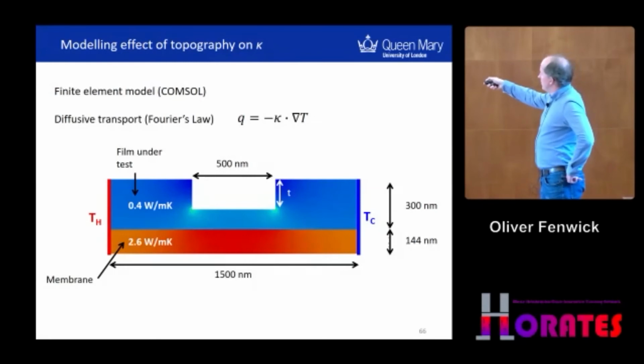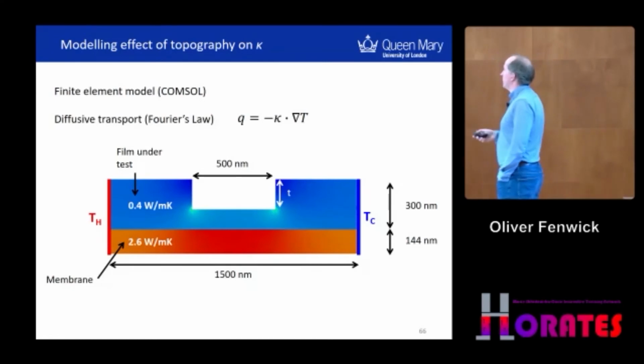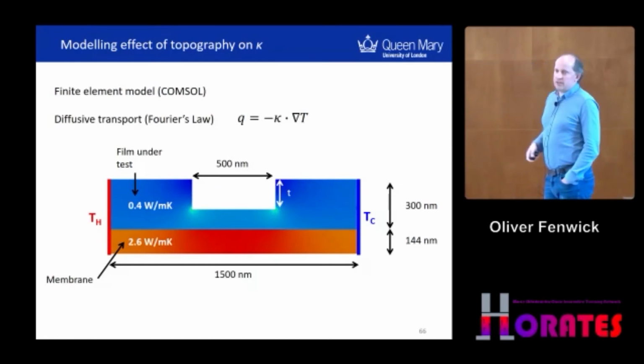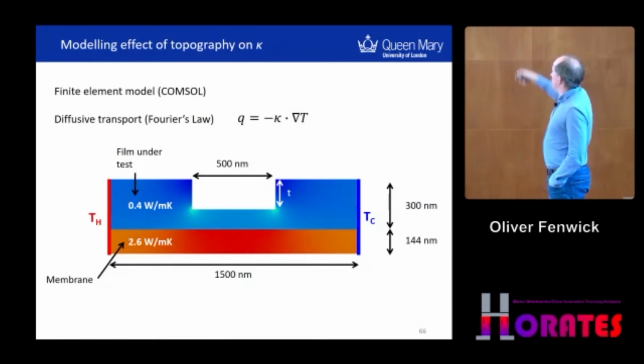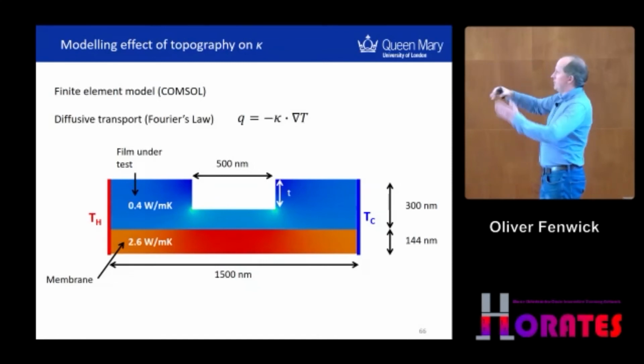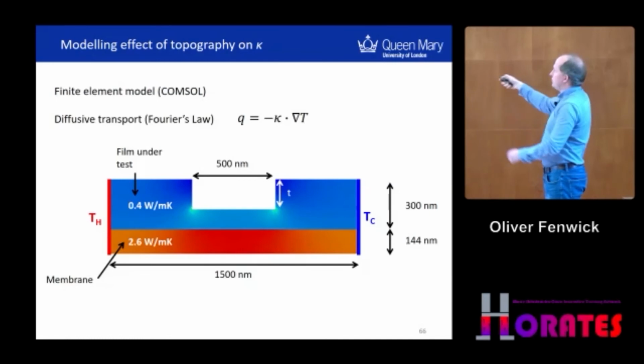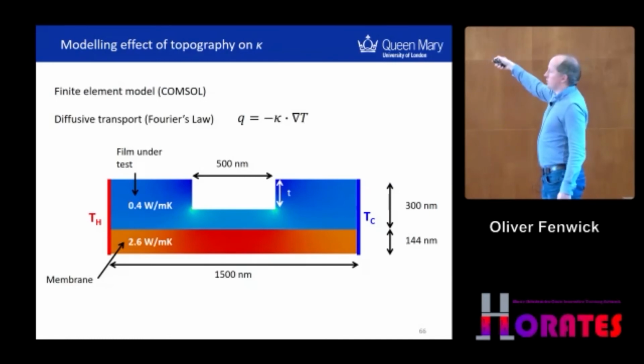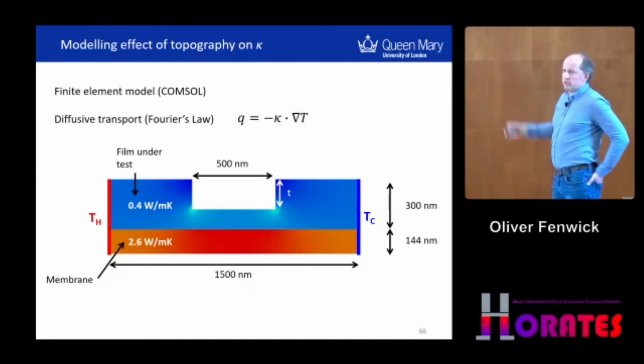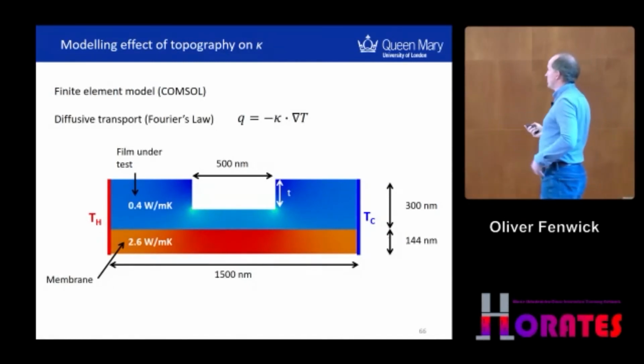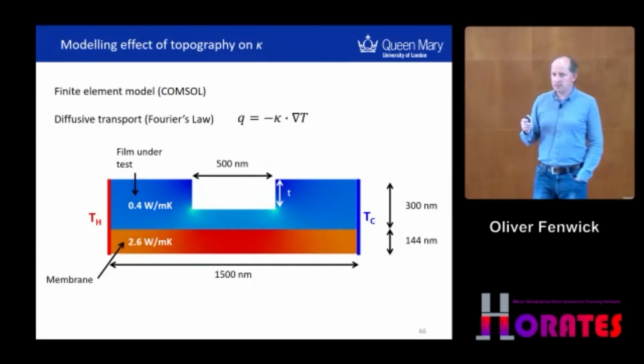At the bottom here, we have the membrane. This is the 100 nanometer thick silicon nitride membrane that we support our films on. On top of that, we have the film under test. It's an organic, so it typically has lower thermal conductivity, say 0.4 watts per meter Kelvin. We set the left-hand side of this simulation to be the hot side, the other side to be the cold side, and we measure the heat flux through this structure as a function of an indentation that we put in the middle. So basically making a thermal constriction in our system to see how our measurement responds to that topography.